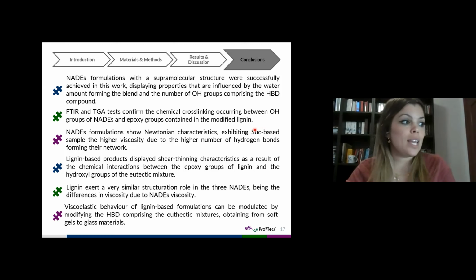Lignin exerts a very similar structuration role in the three NADEs, the differences in viscosity being due to the NADE's viscosity. And finally, the viscoelastic behavior of lignin-based formulations can be modulated by modifying the hydrogen bond donor compound comprising the eutectic mixture, obtaining from soft gels to glass materials.